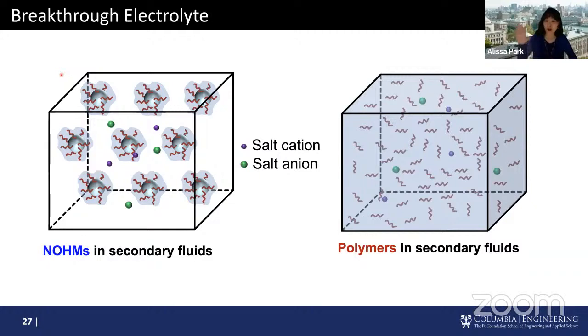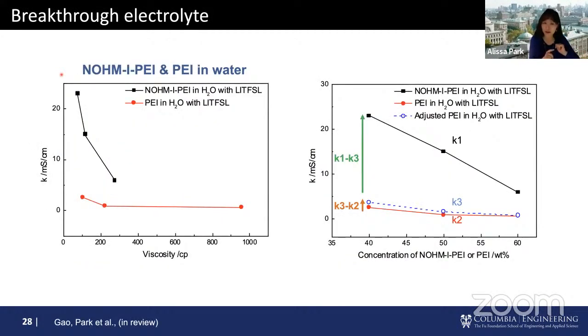What we thought was, since on the right-hand side you only have an untethered polymer, the polymer-based electrolyte should have lower viscosity and higher conductivity. Only thing I was hoping was our NOHM-based system, only difference is it has a whole bunch of nanoparticles running around along with other stuff. We thought if it can perform as well as the polymer-based system or slightly less, we'll still take it. But then results were exactly opposite. We found that conductivity was higher and viscosity was lower for the NOHM-based electrolyte. So we were getting a little confused. Why? Because we definitely have nanoparticles compared to the other case. So we went back a number of times, but still we were seeing the same trend.